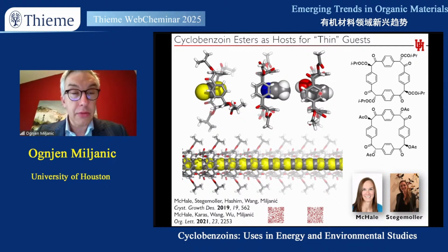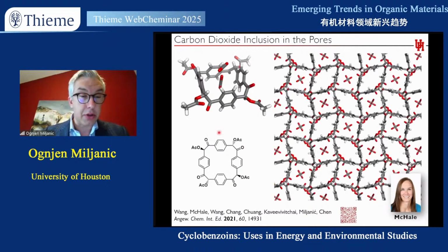And what we're trying to do now is co-crystallize our cyclotetrabenzoin acetate with the ultimate linear guest, and that is carbon dioxide. This sounds like a very improvised experiment, because it was. And so during her studies, she would take a single crystal of cyclotetrabenzoin acetate, put it in a small glass capillary, and then put as much dry ice as she could into that capillary before sealing this structure. So what you see here is these two different orientations. This one, which we'll call vertical, where the carbon dioxide is stabilized by sort of equidistant pi-pi stacking with all four of the benzene rings. Occupancies of both of these positions are significantly under 100%. And so it's not that we have two molecules of carbon dioxide. It's typically one or the other in this orientation.